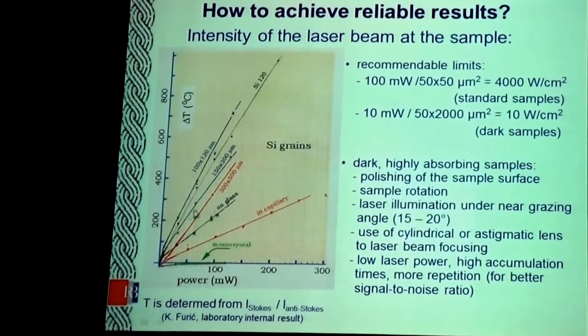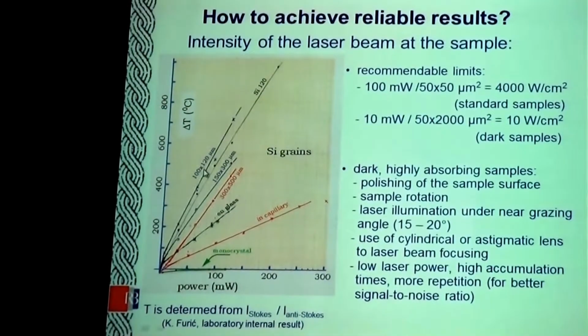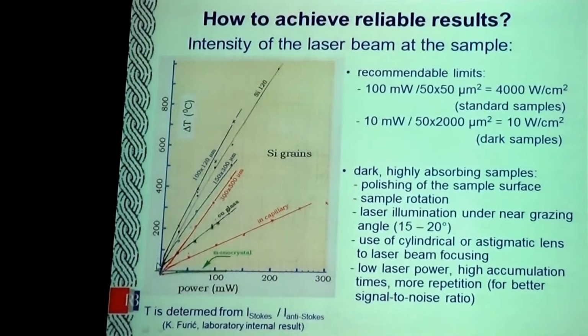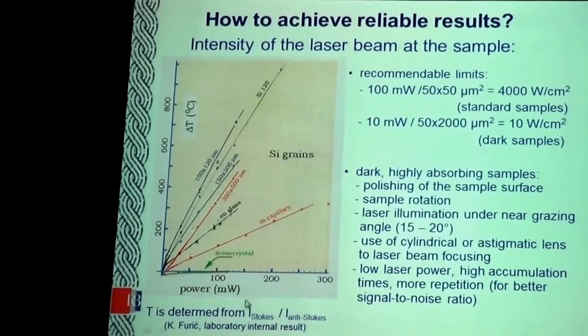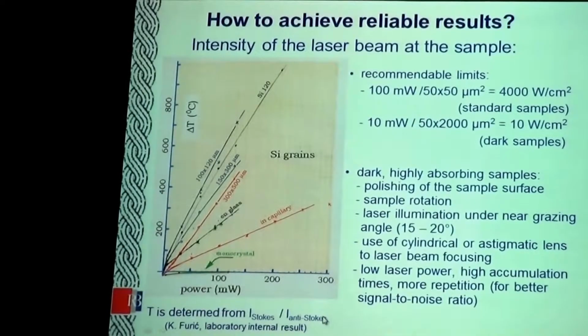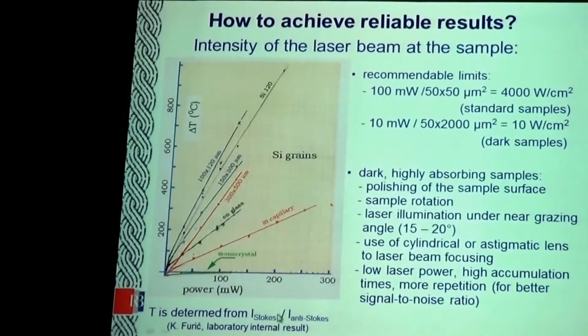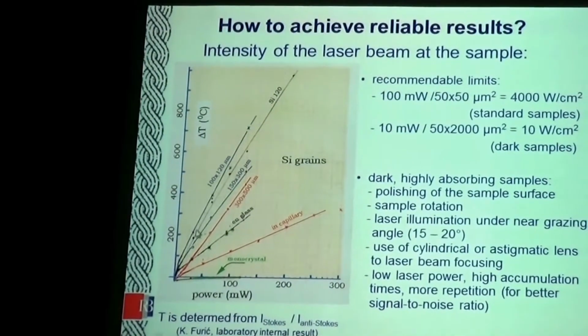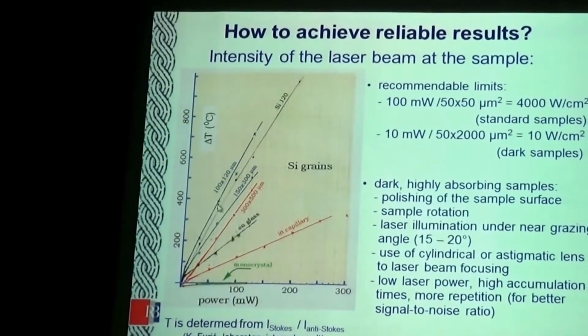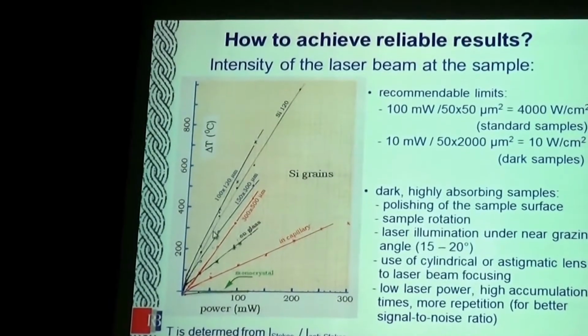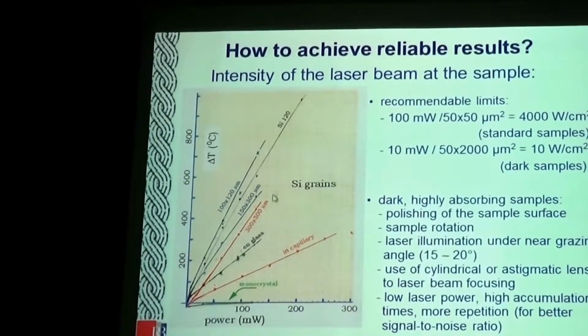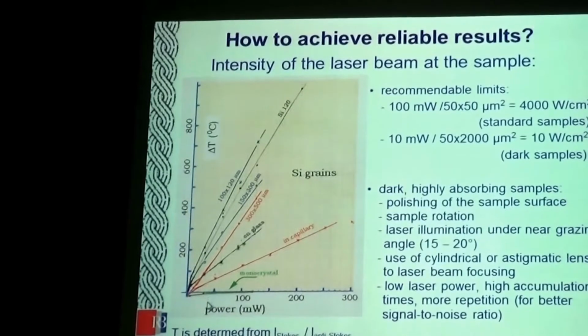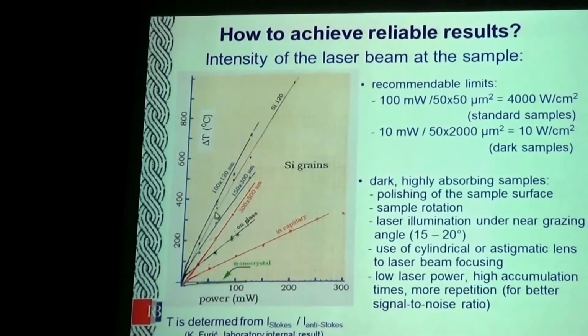So he observed that if you decrease the sizes of the particles, the heating is much higher. As I mentioned, he calculated from the intensity ratio between Stokes and anti-Stokes lines, so he found very large heating. For example, he used silicon grains, even with very small laser power.